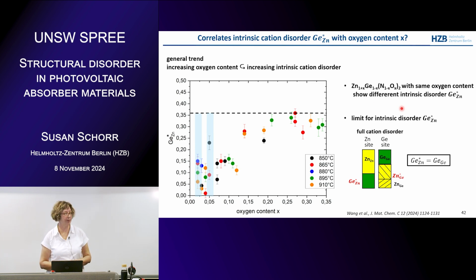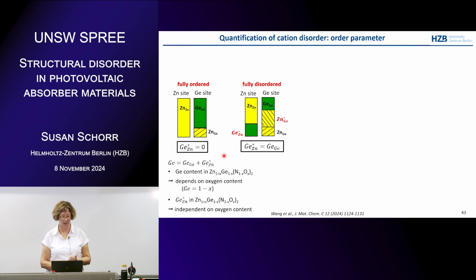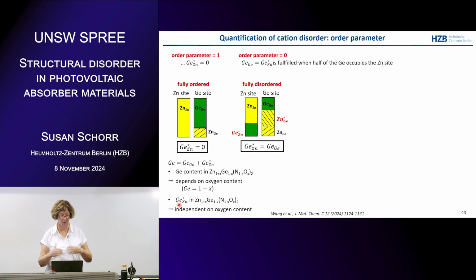And these considerations brought us to the point that we need an order parameter, because otherwise it's all crowded. So we defined our order parameter in the following way. We said, okay, we have these two points, fully ordered or fully disordered. Fully ordered means that we have no germanium on the zinc site, so no green here. Fully disordered means that the germanium on the zinc site is the same as the germanium on the germanium site. The full germanium content depends on the oxygen content, but the antisite defect does not depend on the oxygen content, as we have seen before. So we had to bring these two things together.